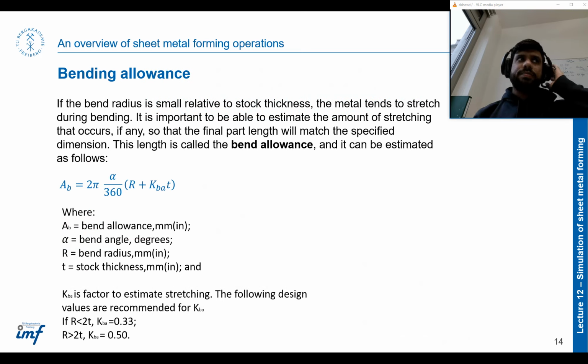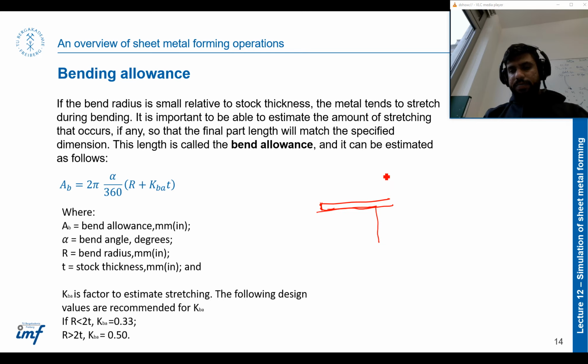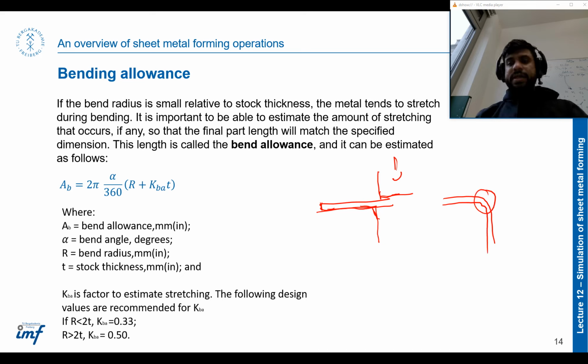It is important to understand that if the bending radius is small relative to the stock thickness, the metal tends to stretch during bending. So, for example, if I want to bend a sheet, let's try to make it as close to reality as it would be, and I put my punch very close, and then I try to force it. What will happen is that this sheet will get thinner at this edge during bending, and that is what we don't want, because it will reduce its strength.